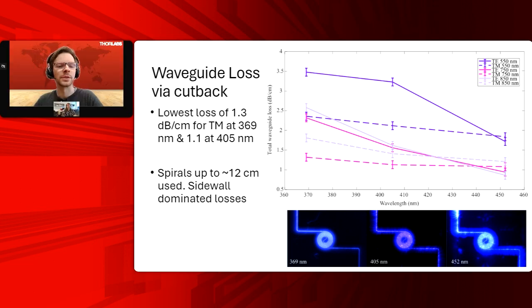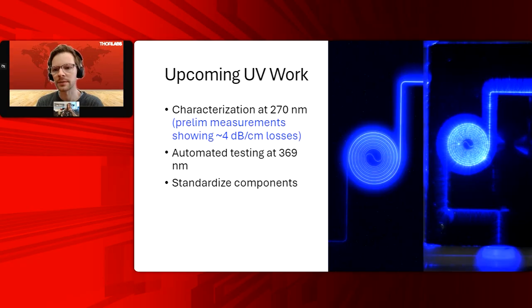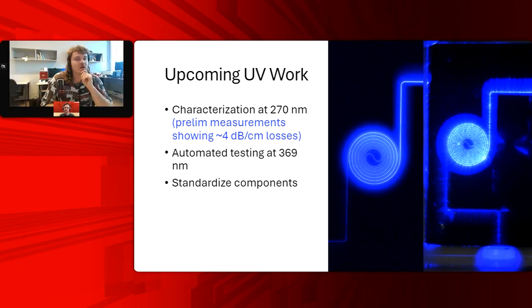And as a quick add-on to that question, with the inverse taper couplers that you design, do you feel like those are more sensitive to the polishing quality or less sensitive than something like a bare cleaved waveguide? I'd say that's something we haven't done in the UV yet, so we're not sure. I'd say it's maybe less inherent because you can get a little bit of a win on having a really long interaction length with these adiabatic tapers. If you design them right, in the UV they will be sidewall dominated, not facet coupling dominated. So it's another reason why it's really cool that if you love the low loss coupling of silicon nitride at the facet edges, then throw that beneath the aluminum oxide and you can benefit from really low facet coupling there with high quality and integration heritage.